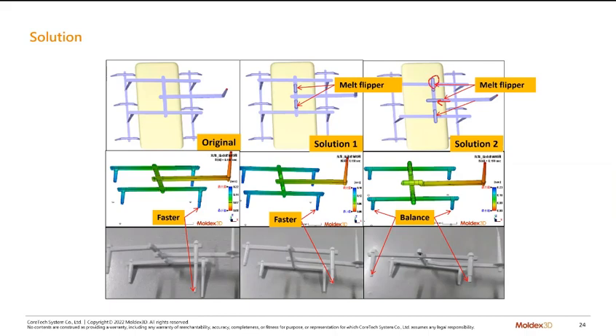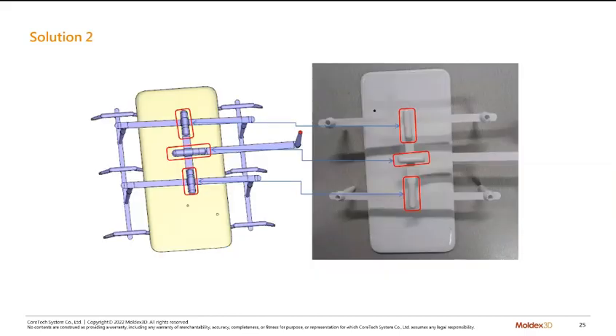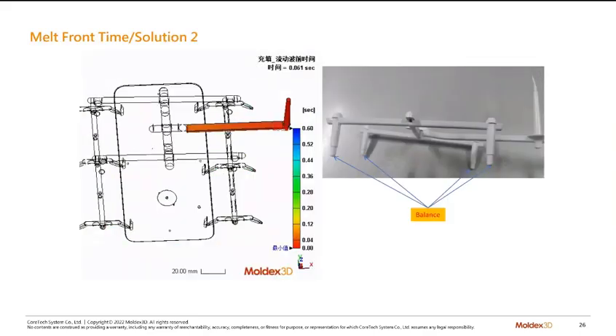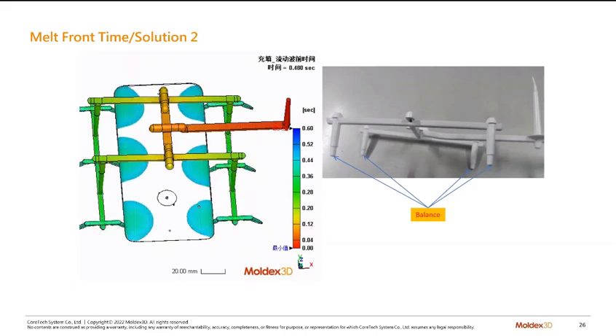And they find out that in the real mold trial or in the simulations, one side is still faster than the other side in solution one. Only solution 2 can have a balanced melt front in both simulation and reality. Okay, so they go for these ones. So they can see that each one is quite balanced.